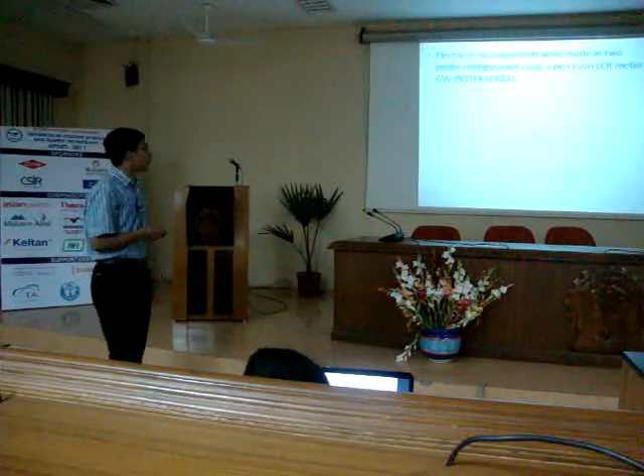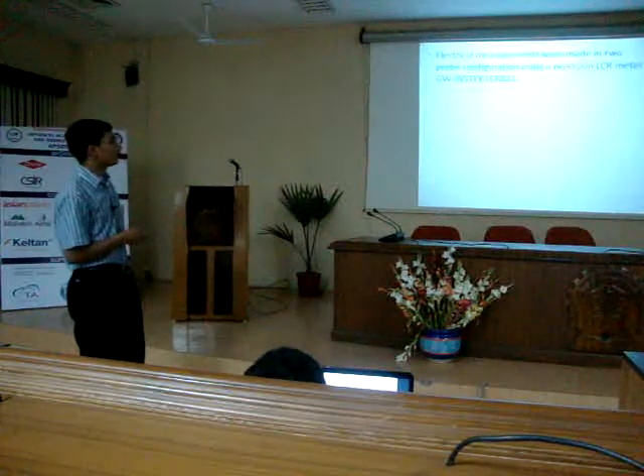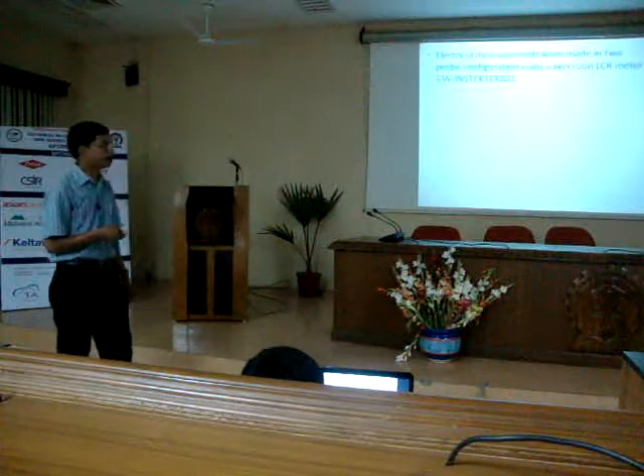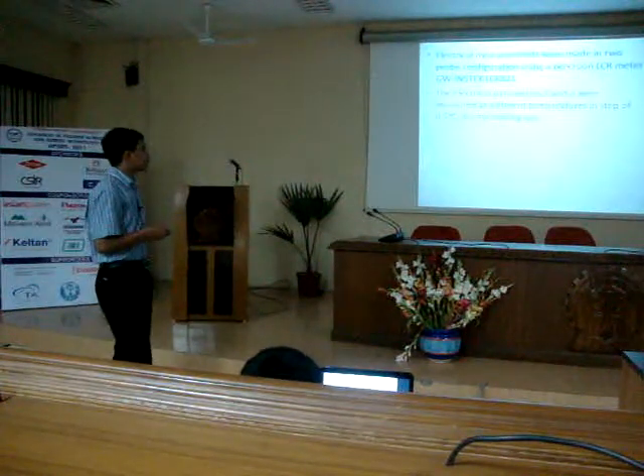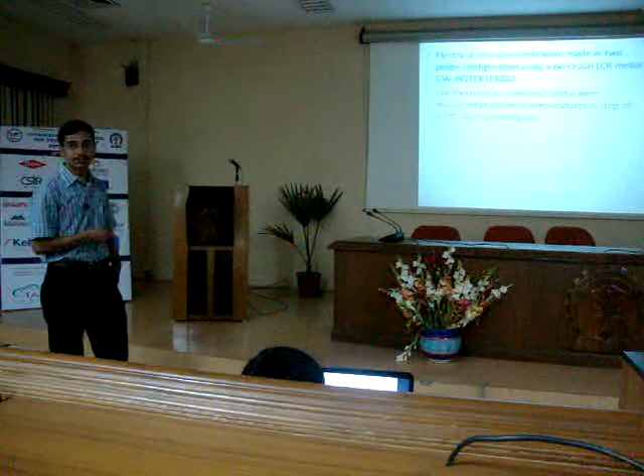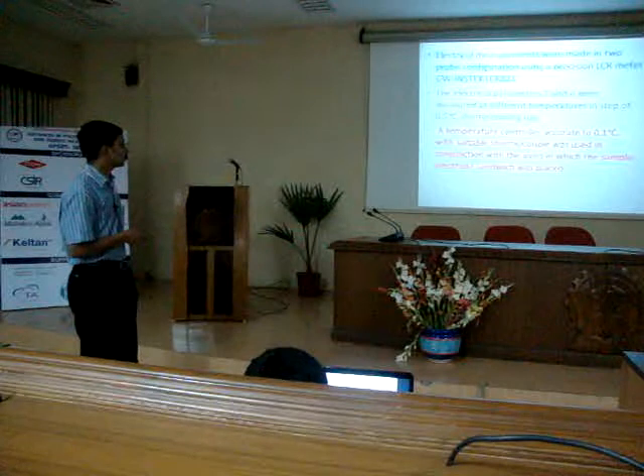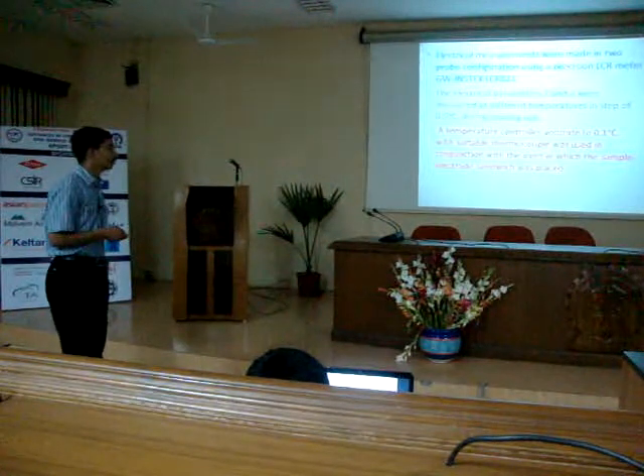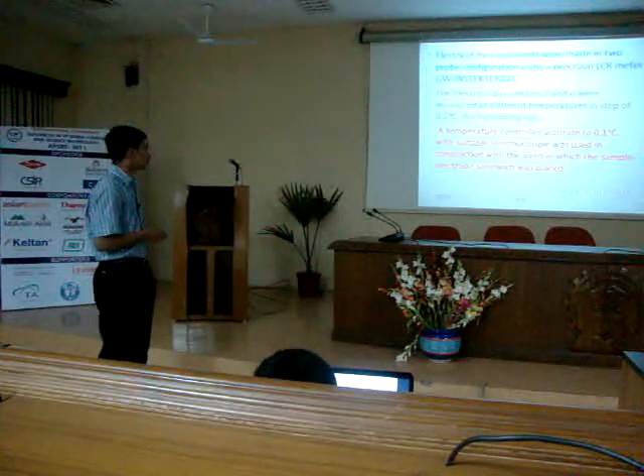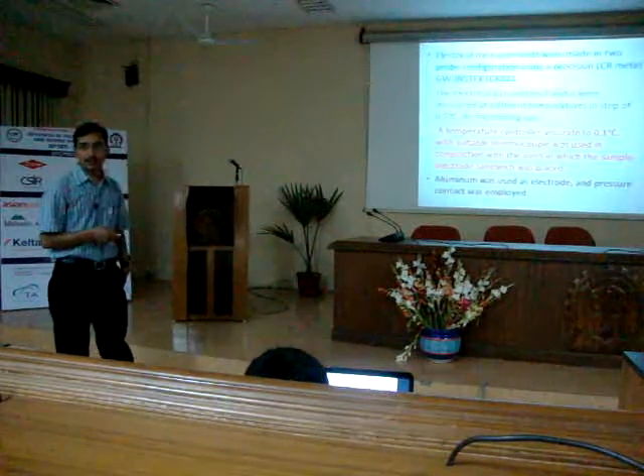So that was for UV visible, and now electrical measurements were made in two probe configuration using a precision LCR meter, GW Instek LCR 821. The electrical parameters Z and theta were measured at different temperatures in steps of 0.5 degrees Celsius during cooling run. A temperature controller accurate to 0.1 degrees Celsius with suitable thermocouple was used in conjunction with the oven in which the sample electrode sandwich was placed. Aluminium was used as the electrode and pressure contact was employed.